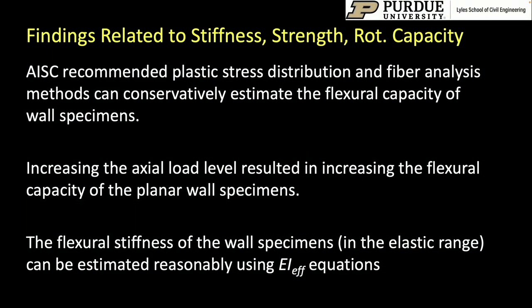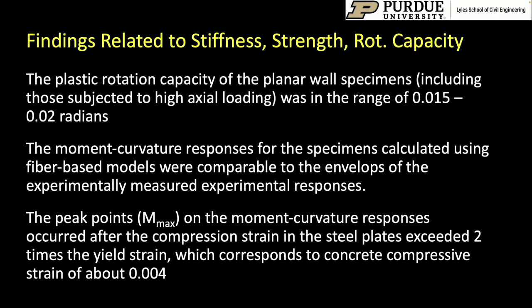So AISC now recommends the plastic stress distribution and also permits the use of fiber analysis to estimate the in-plane flexural strength of the wall specimens. It tells you that if you have axial load, you need to account for that, and it gives you equations for estimating the flexural stiffness of the wall specimens that is based on this research as well. In the commentary, it points out that the plastic rotation capacity of the planar wall specimens was in the range of about 1.5 to 2% in radians, and the moment curvature responses compare very well with the fiber-based models. And it tells you some more recommendations on how to calculate the in-plane flexural strength.